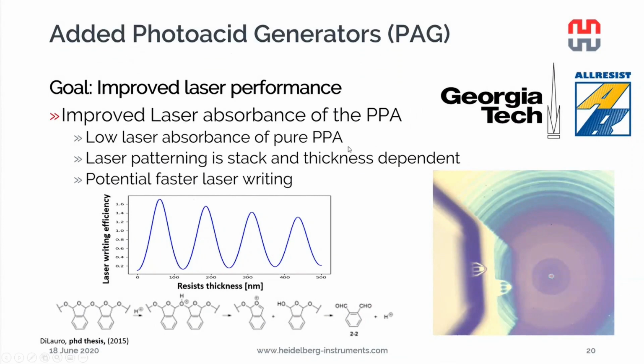One of the goals that we are working on with two partners is to add a photoacid generator, basically a small molecule that upon exposure to light breaks down into an acid. Then, instead of a heat-triggered decomposition, we get an acid-catalyzed decomposition of the PPA. We're not just limited to the laser power, we can also use the light itself as a trigger for the decomposition. This also gives us the potential for faster laser writing. But it's still a long way to go, as we see in this image. With the laser, I just wanted to pattern this tiny little arrow, but a little bit of scattered laser light was enough to trigger the photoacid generator and get a large decomposition on the sample. By accident, we created a photomask with our own cantilever. So this happens, and we have to fine-tune the concentration of the photoacid generator even more.